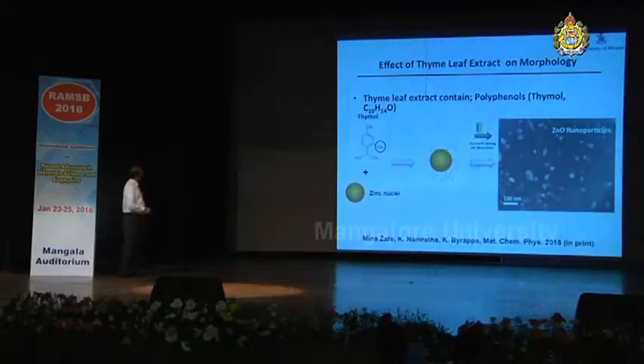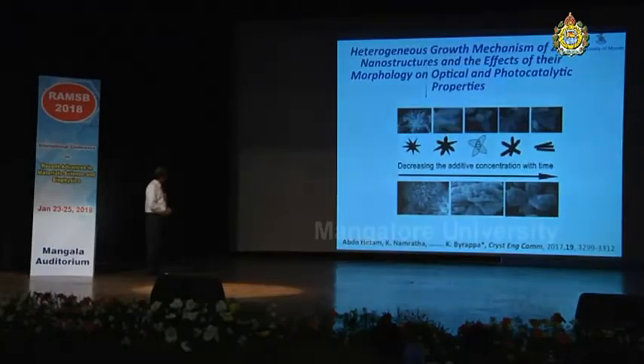And thyme leaf extract has been used as the surfactant biomolecule in tuning the properties, size, shape, and the biological properties, and we get this kind of morphology, and the growth direction is completely changed. Now, we have also discussed the heterogeneous growth mechanism of zinc oxide nanostructures with the additive or surfactant concentration with time, and this was published last year in the Royal Society of Chemistry journal, and this is how the morphology varies with the decrease in the additive concentration.